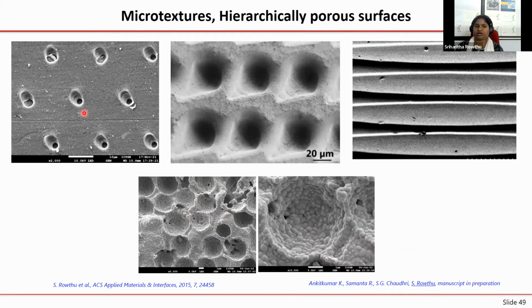So what are the patterns that we were able to prepare? Nice dimples with different geometrical parameters. What are the geometrical parameters? Here we have the diameter, the distance between the cavities, which is called pitch, and the depth of the cavity. Sorry, it's a cavity, not a pillar. And here you can see that they are hexagonally arranged. In principle, I can say that I want them arranged in a square fashion, right? We can do that, or we can also arrange them in a honeycomb manner. So different things are possible. We can also change the area fraction of these cavities. All these are geometrical things, and you can change all of it, fill these with lubricant, and study the tribological properties.